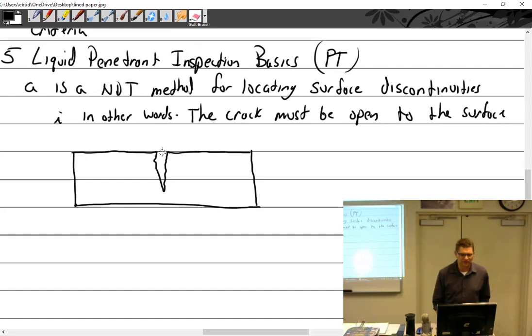That'd actually be a cool project. Just seal up a crack. Do it once with it open and then go media blast it or sandblast it and then see what it looks like after. Okay. Because it's frustrating when you can see the crack, but expose it. Yeah, because what you're looking at is a crack that looks like this, and that doesn't hold penetrant. Well, it does, but not the method we're using. It just washes right out. So you'd need a different type of penetrant for that one.